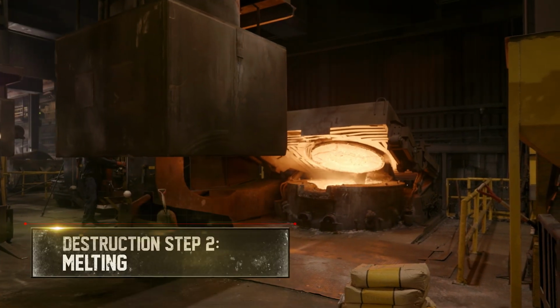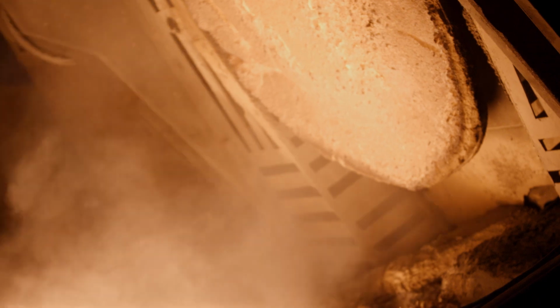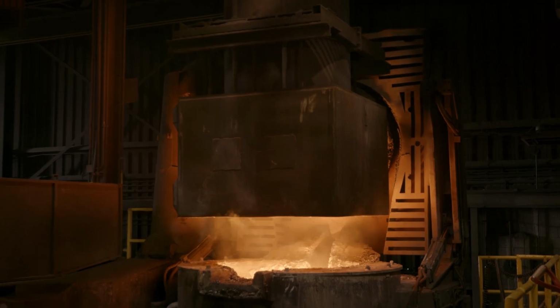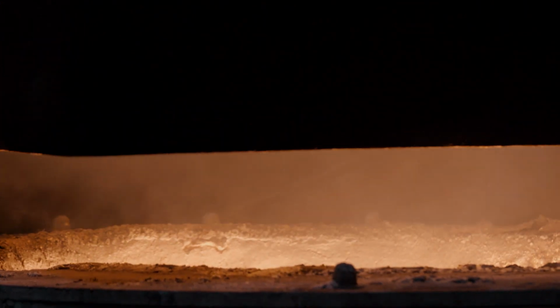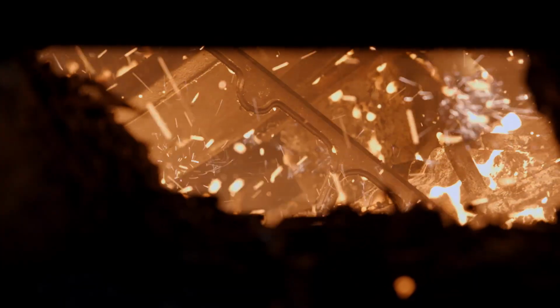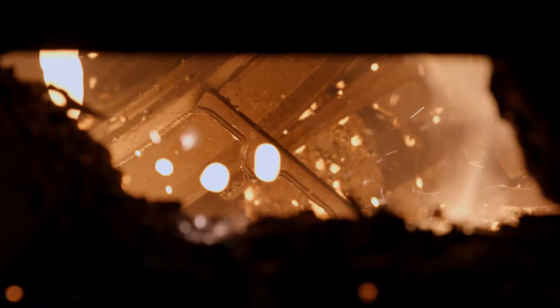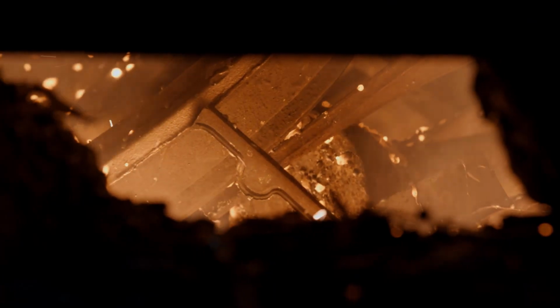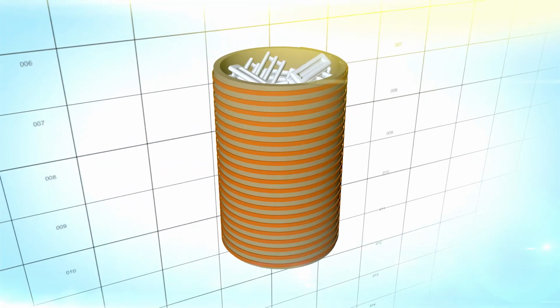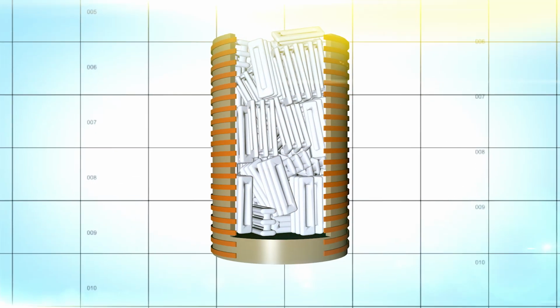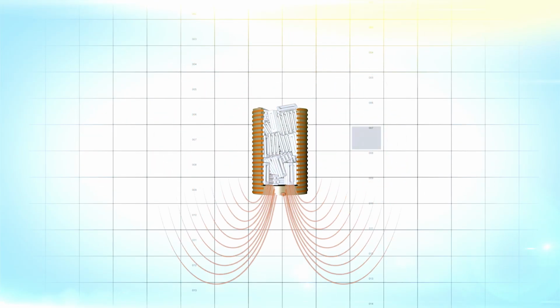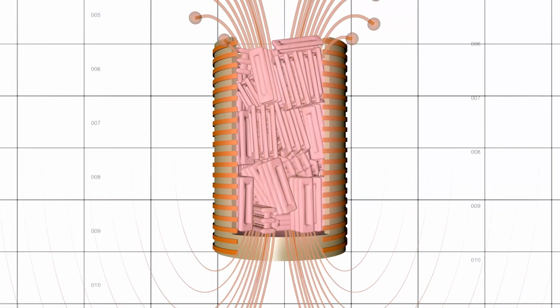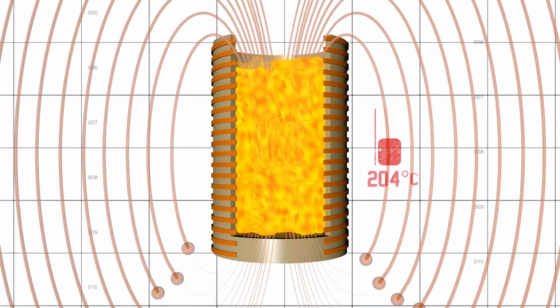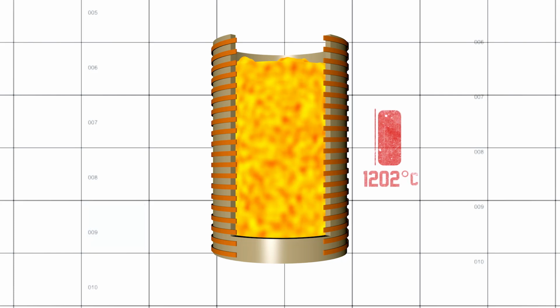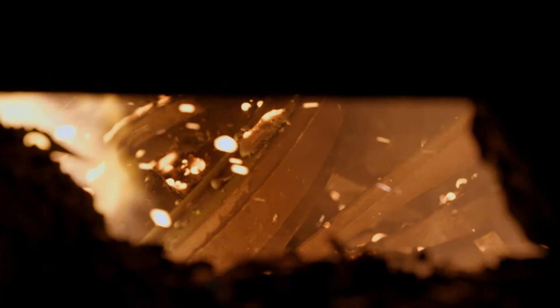A crane carries the charge bucket across the foundry and lowers it into the mouth of a 2.5 meter wide induction furnace. The bucket releases metal into the furnace and it begins to melt. An induction furnace is surrounded by a coil of copper wire. The coil creates a rapidly reversing magnetic field, exciting the atoms in the metal that in turn generates temperatures of 1,300 degrees Celsius. It can liquefy 13 tons of scrap every hour.